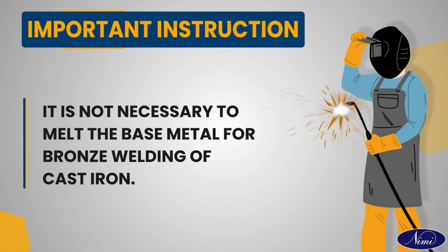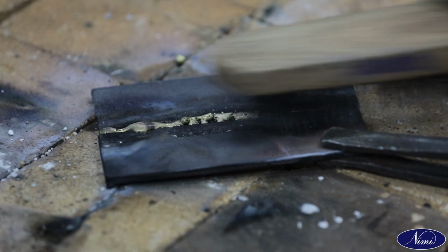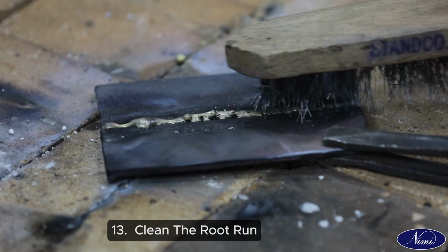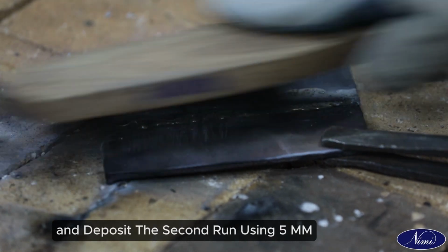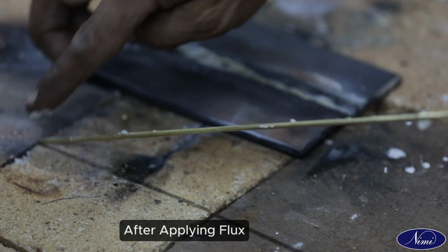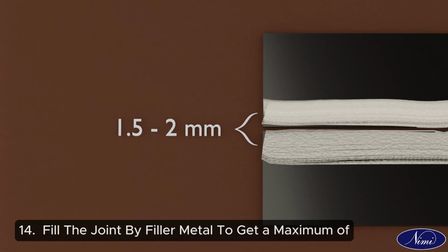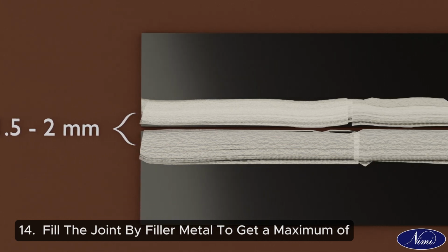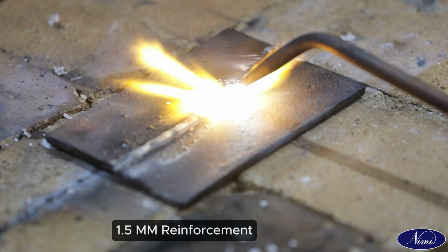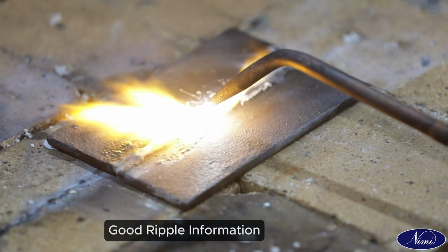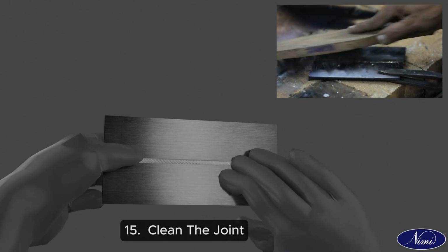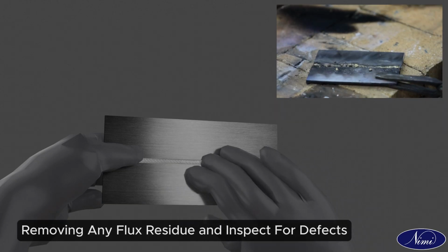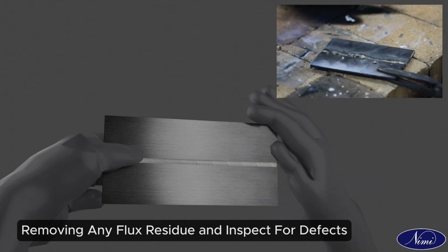Important instruction: it is not necessary to melt the base metal for bronze welding of cast iron. 13. Clean the root run and deposit the second run using 5 mm filler rod after applying flux. 14. Fill the joint with filler metal to get a maximum of 1.5 mm reinforcement, with good ripple formation. 15. Clean the joint, removing any flux residue, and inspect for defects.